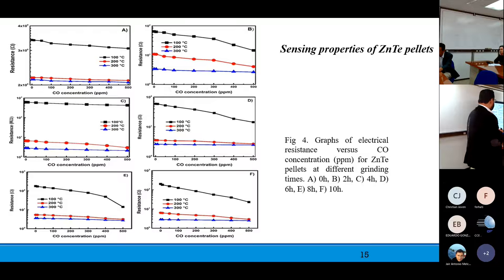We measure the sensing properties of these zinc telluride pellets. These sensing properties were measured to register the resistance versus the CO concentration in ppm at different operating temperatures. We can observe that the materials have a good response at lower temperatures, and the resistance decreases with the milling time in all the cases.